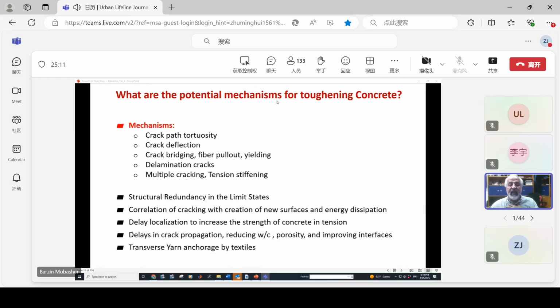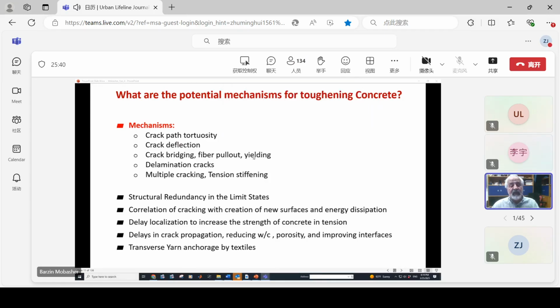So what are the potential mechanisms by which I can toughen the concrete? Everybody has done this, and we know it, but the question is, how do we bring them into formulation? One of them is crack path tortuosity: allow the crack to go through so many different paths, deflect the cracks, make them just break apart and dissipate the energy. Crack bridging, fiber pullout, yielding. All of these are energy dissipation in the system. That's what we want. We want to spend so much energy, and that increases the toughness, which means that the energy required for growth of the crack is not available anymore.